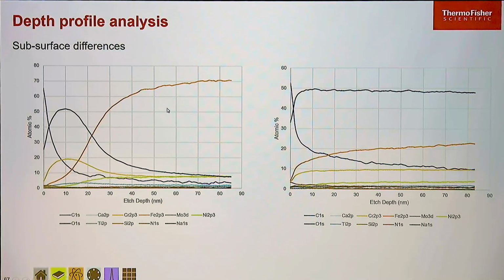So for steel, for looking at these passivation layers, if they're thin enough, we can do it just directly, just looking at the surface and calculating the ratio of oxide to metal. If it's a bit thicker, then we use depth profiling to etch through the samples and determine the differences and understand why we might be getting failures.